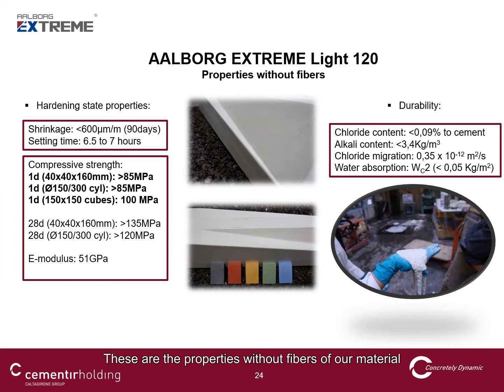These are the properties without fibers of our material, the hardened state properties. We have a shrinkage of less than 600 microns per meter at 90 days, setting time between 6.5 to 7 hours, and a very high one-day compressive strength. In prisms it will be more than 85, also in 150 by 300 cylinders and 150 by 150 cubes, 100 megapascal, and 28-day compressive strength more than 135 in prisms and more than 120 in big cylinders. The E modulus is around 50-51 gigapascal.